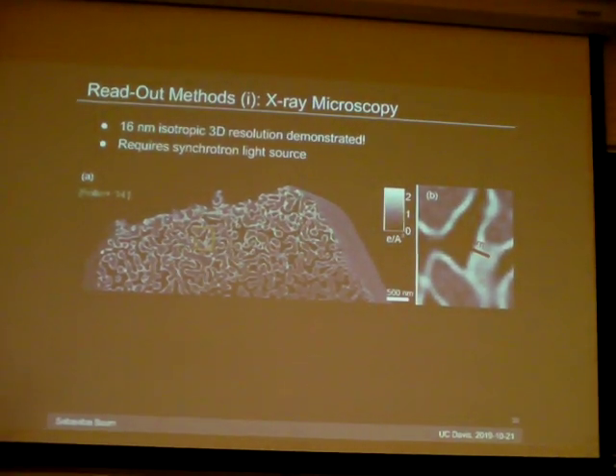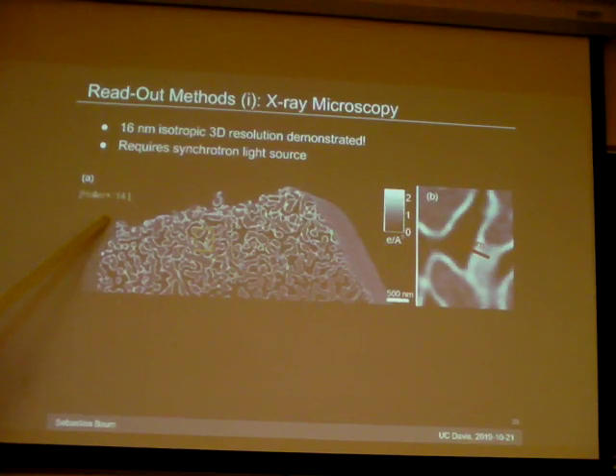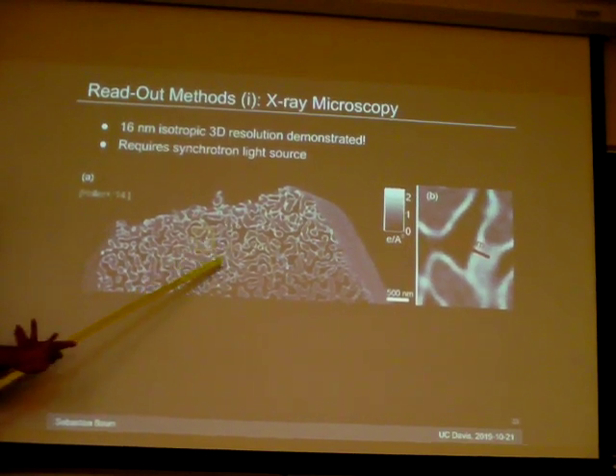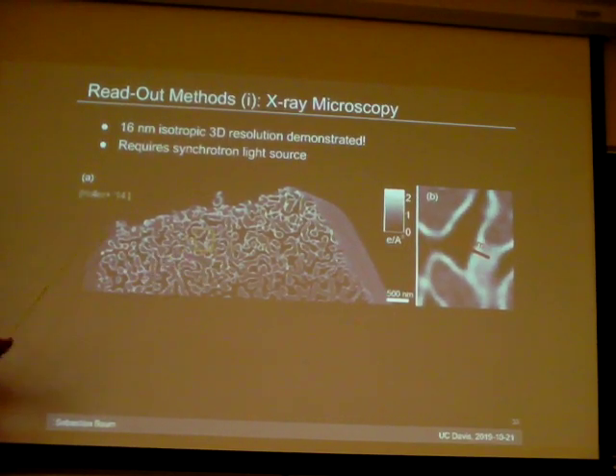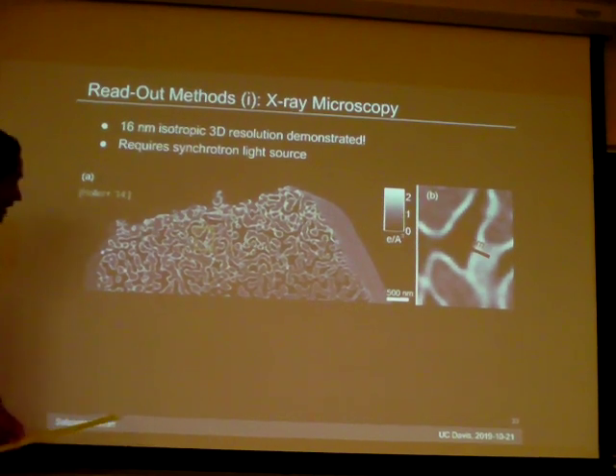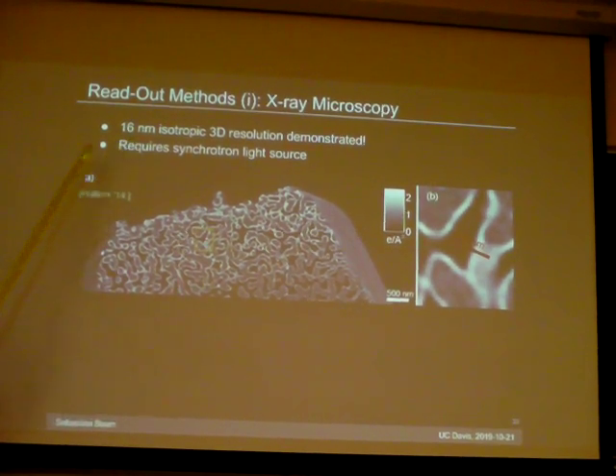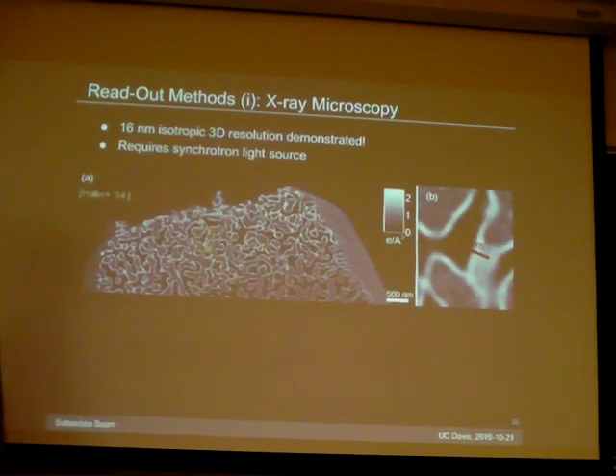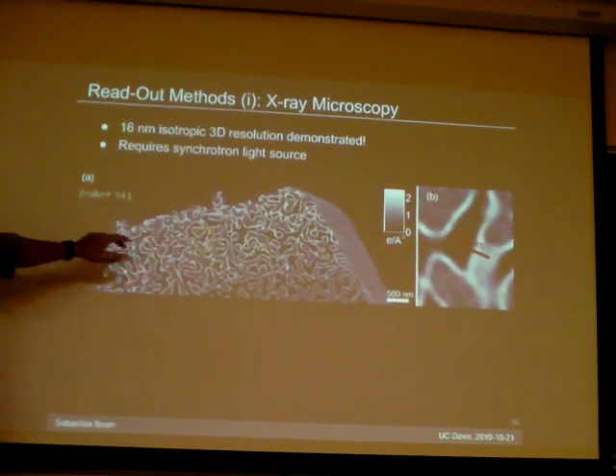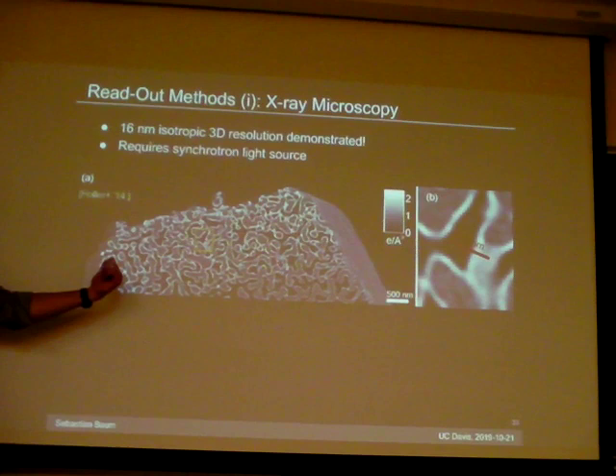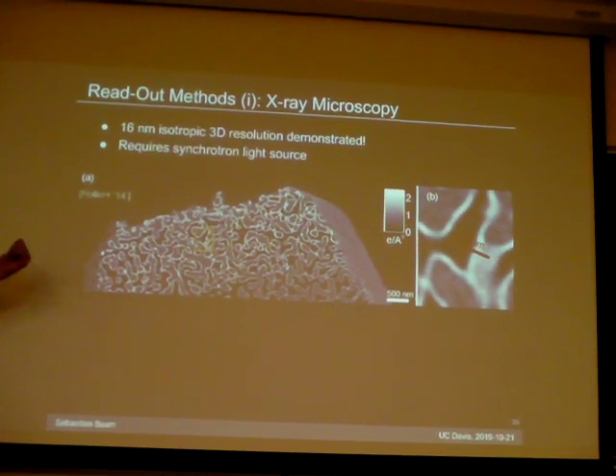This has been demonstrated. This is just a show-off picture these people have produced. They took a glass colloid just to show off the spatial resolution you can achieve. This has been done in Switzerland at PSI. They've demonstrated 16 nanometer 3D resolution in a bulk sample. The downside, of course, is you need to have a synchrotron light source for this. Now, you see, of course, I'm not showing you a picture of a track, right? The reason for that is that this has not been done for tracks. Tracks have been reconstructed with small angle X-ray scattering, but not at these resolutions.